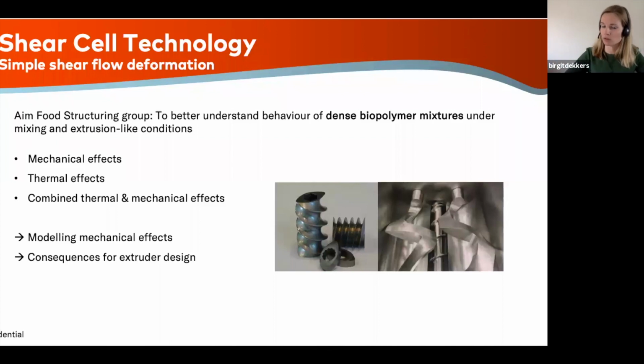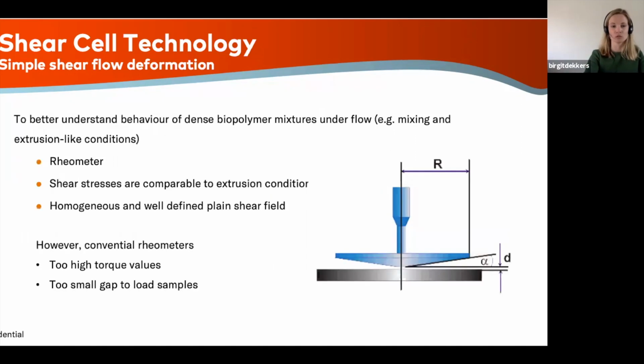And then the idea was that you can better design your extruder-like processes. Well, to do so, to better understand these behaviors of dense biopolymer mixtures under flow, you can think of how to simplify these processes. For example, by using a regular rheometer. Because the shear stresses that you can apply in a rheometer are comparable to extrusion conditions. Although, of course, the flow field is more homogeneous and well-defined, and you have a plain shear field instead of all these complicated flows. But this was the approach that was taken in the very early days, I have to say.